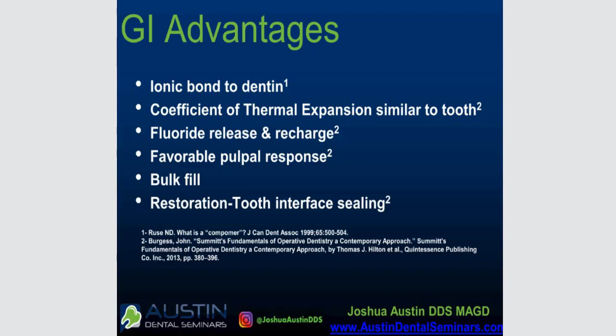Another aspect that we see of glass ionomers that we can take advantage of, and is very beneficial for our patients, is the fact that after a glass ionomer restoration is placed, we see more of a seal at the interface between the restoration and the tooth. And a big part of that is that we really don't have much, if at all, polymerization shrinkage of glass ionomers versus that of resin composites, right? So you place a resin composite, you have polymerization shrinkage, you get some opening of that restoration tooth interface that can cause some sensitivity and bacterial leakage and stained margins and all that. And you get much less of that with glass ionomer. And that's the thought, that because there's no polymerization shrinkage, or orders of magnitude less than resin composites. So those are 6, I think, advantages that you can find about using a glass ionomer restorative material.